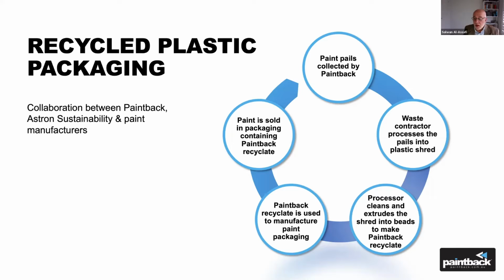After that, an important step in this process is polymer sorting, because this is a waste industry. You do get all sorts of other materials, other polymers. You cannot really have very good control over what people put in these collection centers. So we go through a process to polymer sort the shred. We remove all other polymers and just keep polypropylene. Normally we get a lot of PE, polyethylene, so we remove all the polyethylene, and then we end up with a fairly high percentage of polypropylene. This polypropylene, we extrude it, pelletize it, and then we end up with polypropylene beads or pellets.